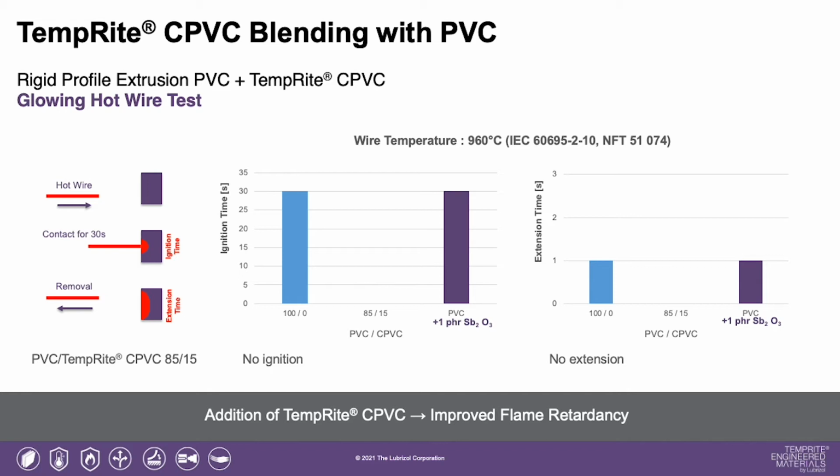The relevant sections of the IEC 60695 standard specify the details of the glow wire test to be applied to test specimens of solid electrical insulating materials or other solid materials for flammability testing to determine the glow wire flammability index, GWFI. The GWFI is the highest temperature determined during this standardized procedure at which the tested material does not ignite or, if it does, extinguishes within 30 seconds after removal of the glow wire and is not totally consumed by the fire. In addition, molten drips, if they occur, do not ignite the wrapping tissue.